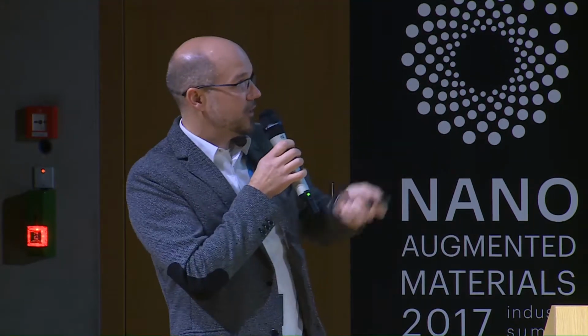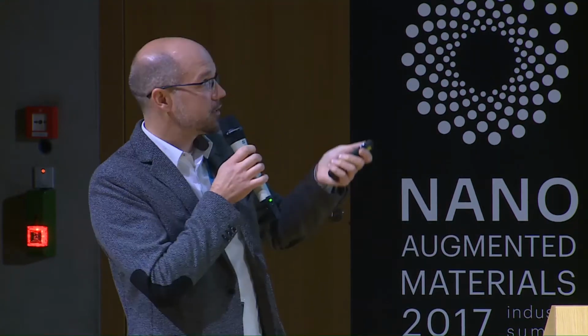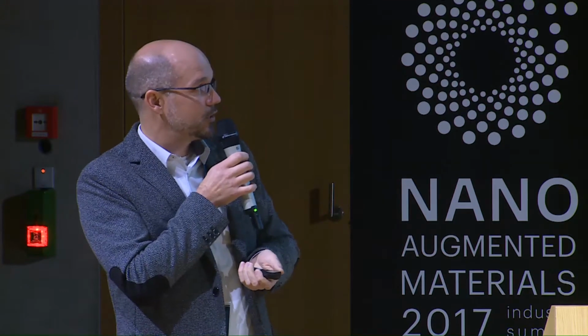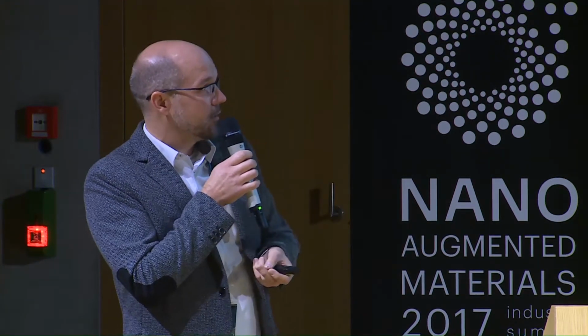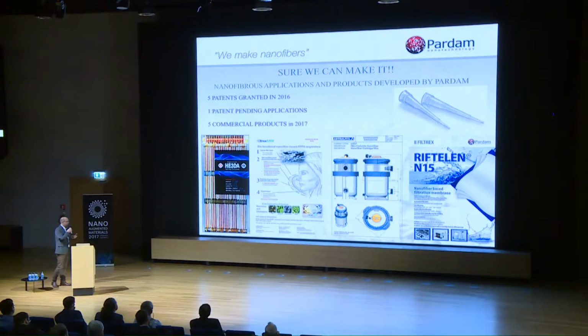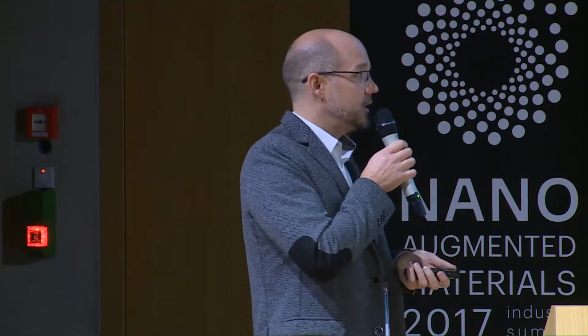Again, it's an antibacterial nanofiber-based membrane which is used for creation of breath masks. We have developed a membrane for swimming pool filters together with Astral Pool. Or actually, Astral Pool is selling the filter, but we developed it with one of the Spanish companies. And the filter has several advantages against sand filter. We have better filtration efficiency, higher flow rate. We have much smaller and lighter equipment, like 3 times smaller and lighter. You need much less water to clean the filter.